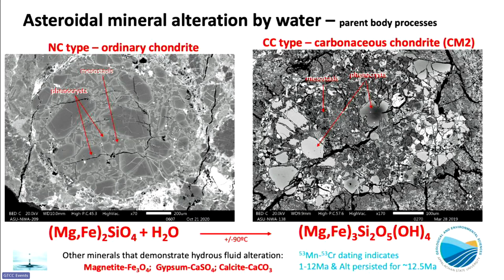All the mesostasis material in between the phenocryst has been transformed into this phyllosilicate mineral that is a serpentine. And we can see the addition of that water in the chemical formula. Now we know this process happens at relatively low temperatures because we haven't lost the chemical zonation that has to be retained during the low temperatures. We also see the appearance of other mineral phases that show they've been altered by aqueous fluids and oxidized.